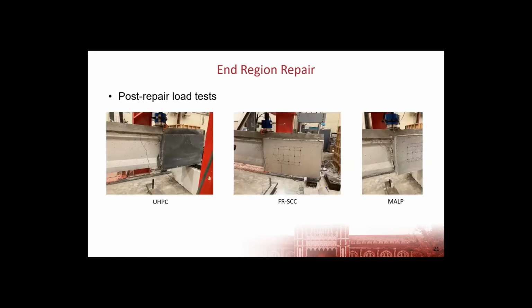We then completed post-repair load tests using the same configuration that we did pre-repair, which was a single point load about 4.5 feet from the end of the beam. And these pictures are all post-testing. So you can see the cracking patterns in each one of them. You can also see that there's not a lot of cracking that was observed.